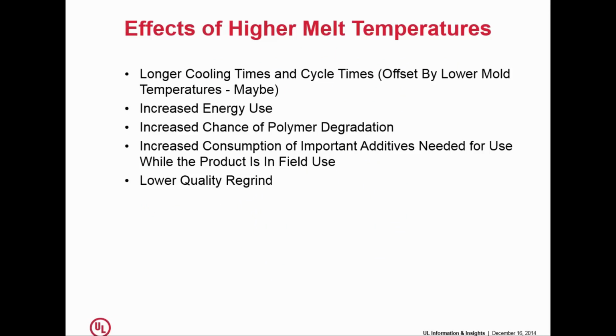Now, I mentioned before that most people I run into are using melt temperatures that could afford to come down. And a lot of times there's a lot of denial associated with that. A lot of times you come in and say, well, you can turn that temperature down 20 degrees. No, we can't. No, we can't. And then when you get into it, you find out, well, yeah, you really can if you're willing to use the capabilities of the equipment to their fullest and if you have the right kind of equipment. But let's assume that you are running higher melt temperatures than you need to.